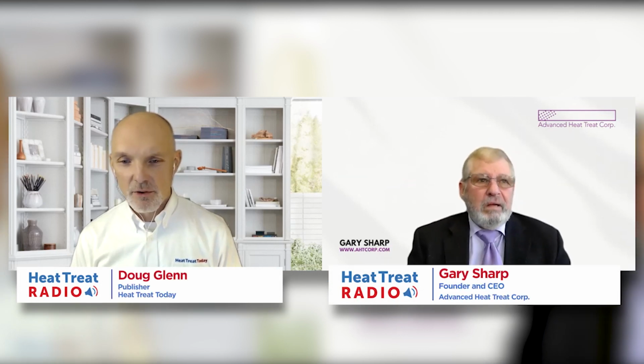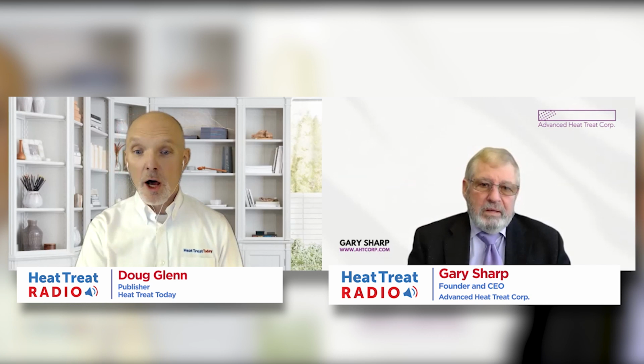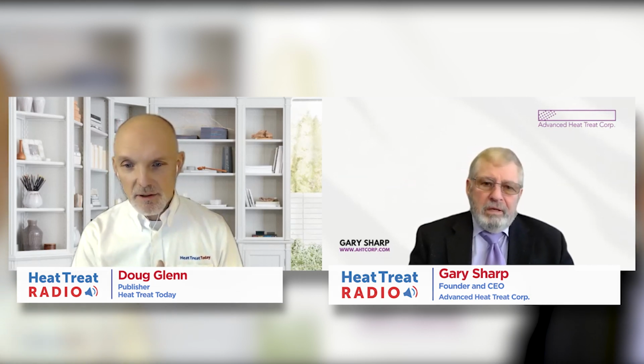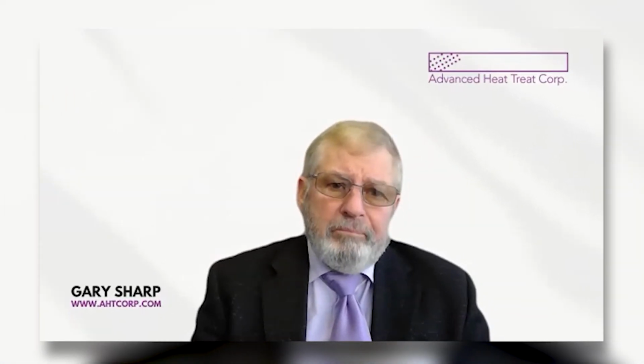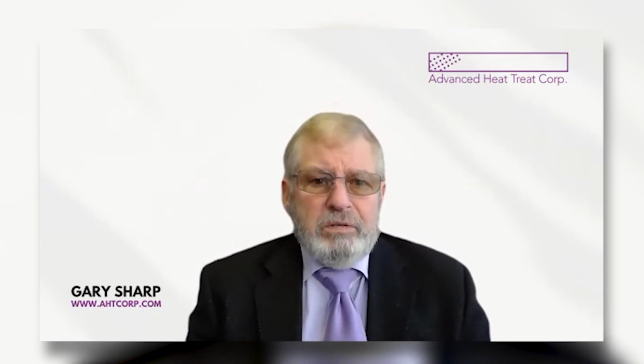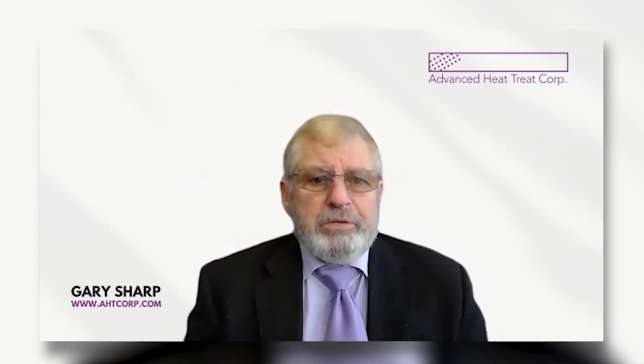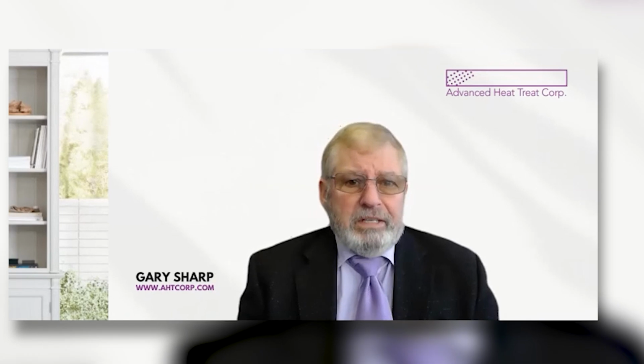So we've got certain benefits there. Basically, any industry you're saying can do it if there's anywhere where there's high resistance. So automotive parts, yes. Automotive, aerospace. We did the submarine gear for the Seawolf submarine, 35,000 pounds, 160-inch diameter. And that ran probably 400 plus hours, not because it was big, but because they had an extremely deep case requirement. So the diffusion took longer, particularly at the lower temperatures that you run versus other kinds of treatments.